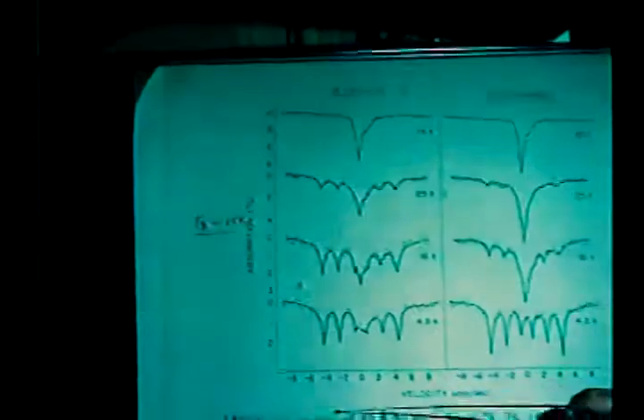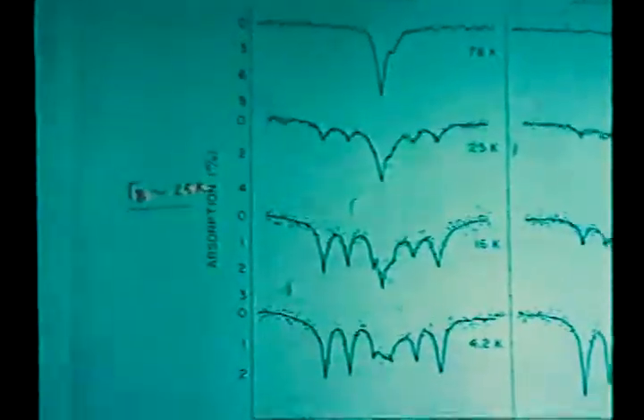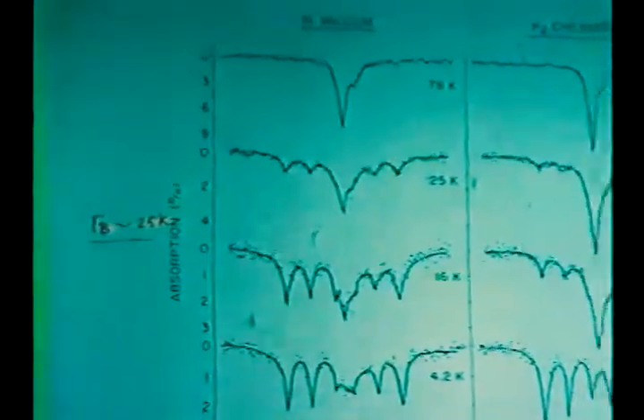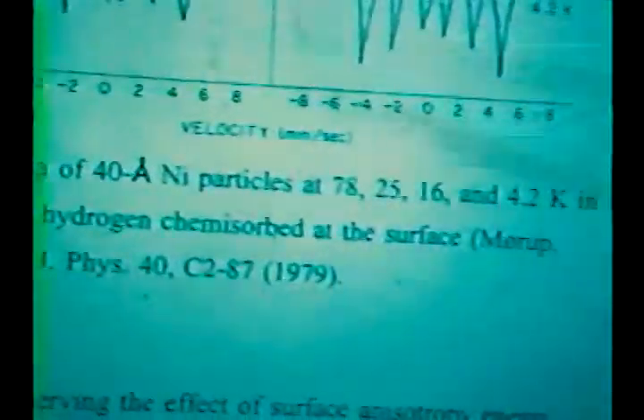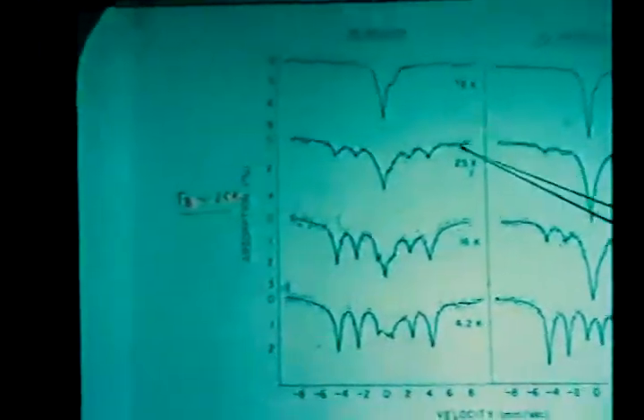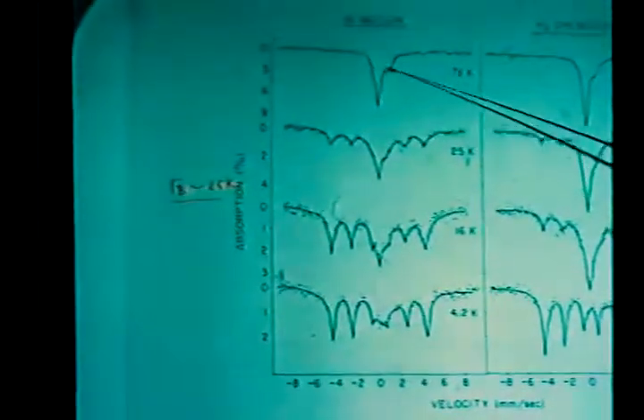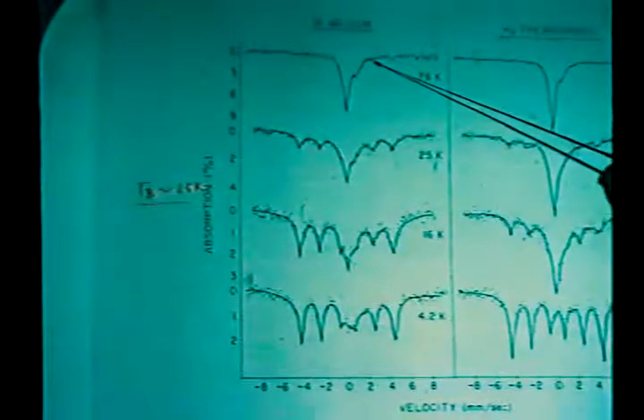First, I'll give you an example. This is a nickel particle, 40 angstrom, measured at different temperatures by Topsøe and Mørup. The left is the particle in vacuum at 78 K, and this is typical for a paramagnetic spectrum.